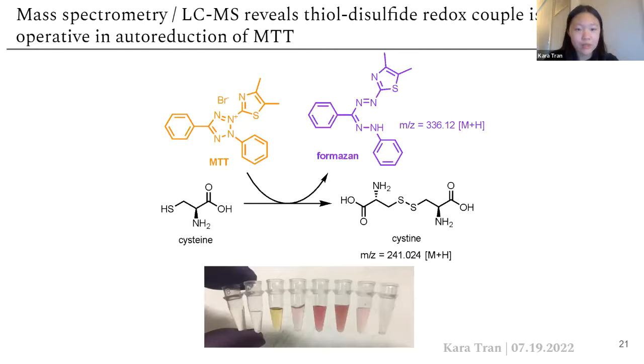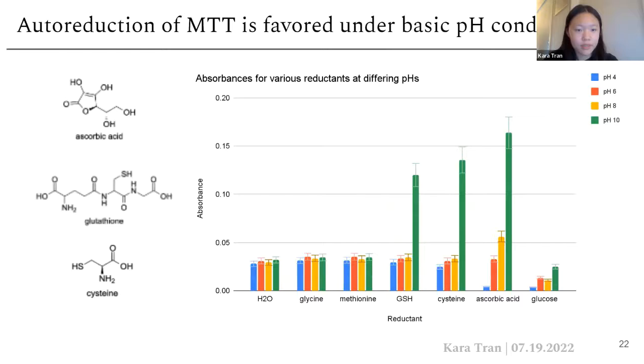We then utilized mass spectrometry, or LCMS, to determine the mechanism by which this autoreduction occurs, finding that a thiol-disulfide redox couple auto-reduces cysteine into cystine. However, the mechanism for ascorbic acid is a bit more complicated and we're currently working on it. In our next trial, we tested again, and cysteine and glutathione have higher reduction, though interestingly, much higher at a pH of 10. What this tells us is that these 3 reductants are likely interfering with the reduction in the MTT assay.